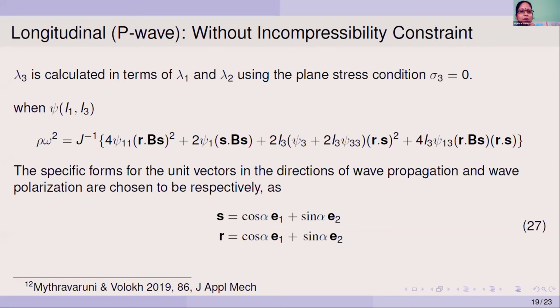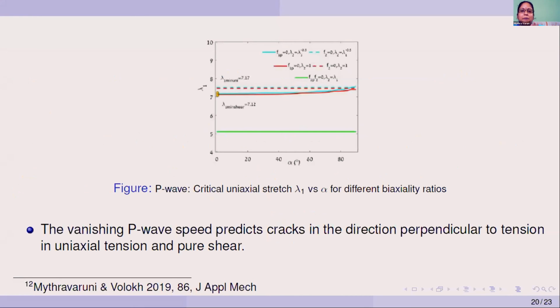So we use the expression for the wave speed and the specific forms of unit vectors, and we obtain the split conditions in the case of compressible material when we superimpose longitudinal pressure waves. Here we have plotted lambda 1 versus alpha, and in case of equibiaxial tension, we can see that for this green line,